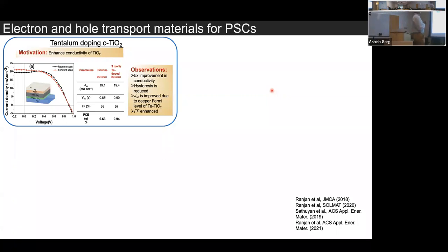It increases the electron density in the TiO2 layer. What we find is that the improvement in the conductivity of TiO2 is about 5 times when you incorporate tantalum in this lattice. The second good thing is that our hysteresis is almost vanished. The devices without tantalum doping of TiO2 have higher hysteresis, but here the hysteresis goes down. We also obtain a higher fill factor as well as performance of the devices.